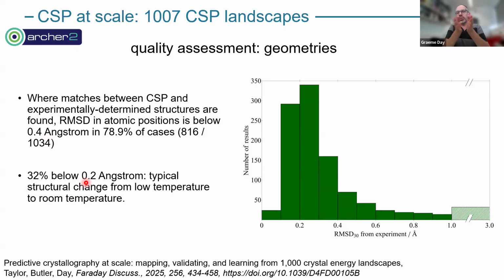I point that out because, again, we've ignored thermal contributions in our energy calculations. If you compare cases where you have an experimental structure which has been determined at room temperature and at low temperature, then you find that you typically get differences of up to about 0.2 angstrom. So all of these differences here, sort of below 0.2, can be explained again by the fact that we haven't included thermal contributions.